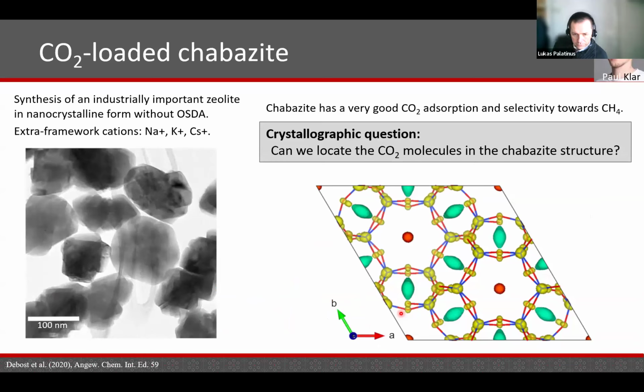The next example comes from the field of framework materials. This was a collaboration with the group of Svetlana Mintova in Caen, in France. They produce zeolites for various applications, and in this case, they produced specifically nanocrystals or very small crystals, as you can see here, and they analyzed the absorption capacity of that material with respect to selectively absorbing CO2 and not methane. And the crystallographic question was, can we see the place where the CO2 molecules are absorbed in the structure?